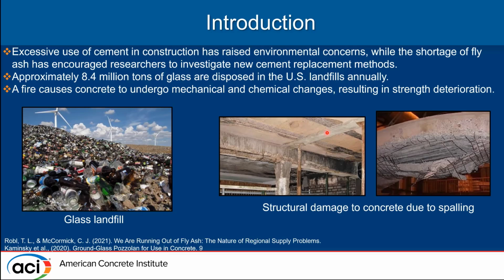So concrete, when heated, its relative humidity tends to increase with the increasing temperature, and because of this, higher water content results within the concrete matrix, and at higher temperatures, this water is converted to steam, and that steam increases the pore water pressure, which results in the spalling of the concrete. And I have a few images that show how the structural integrity of the structure is damaged.